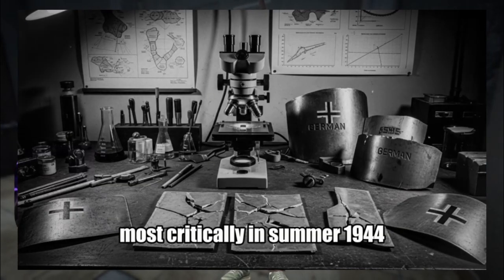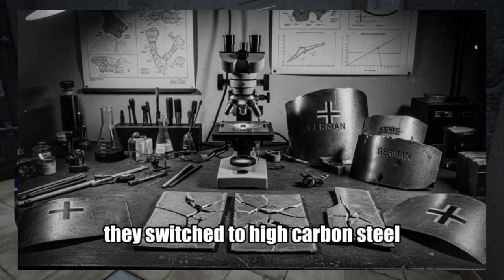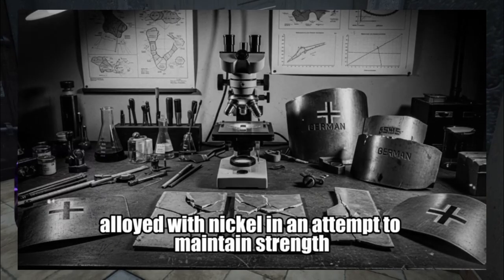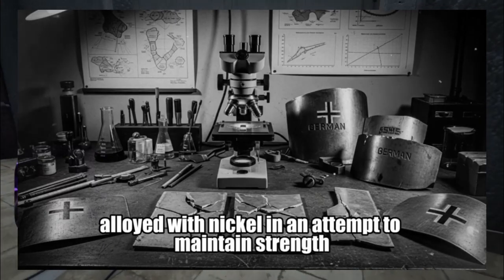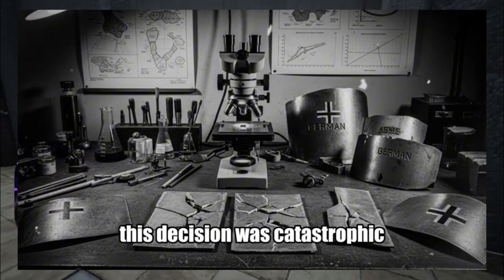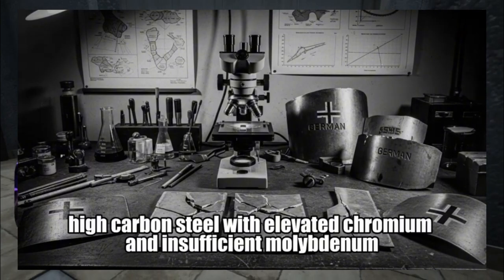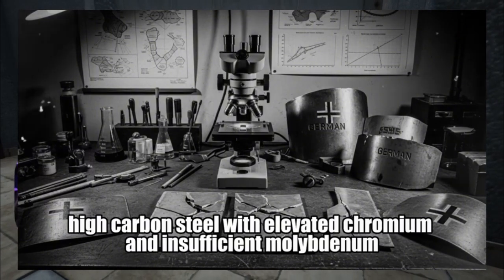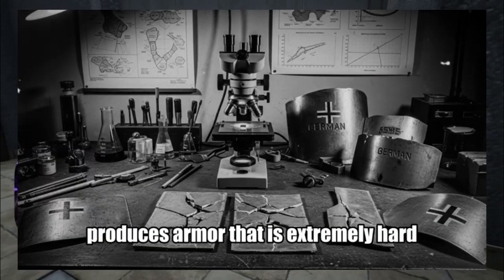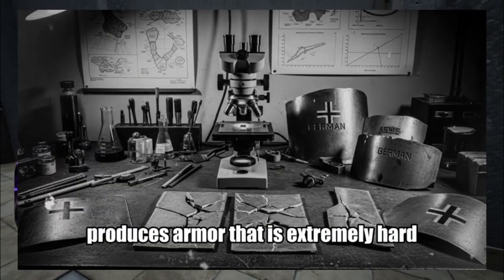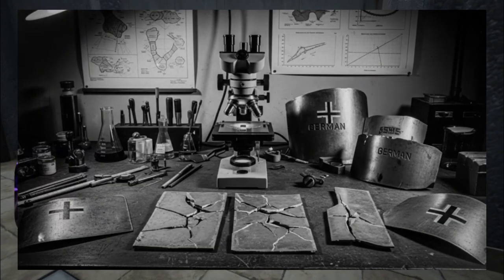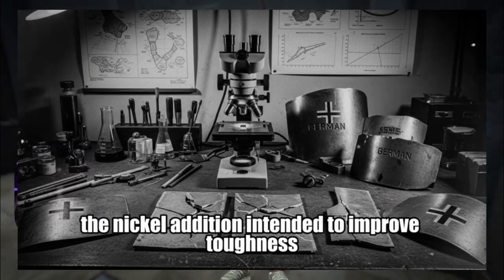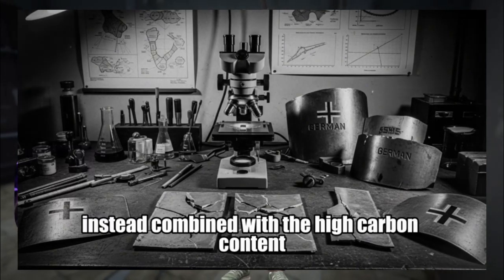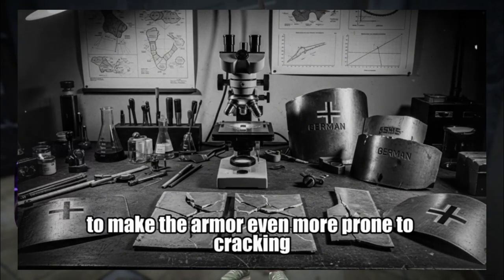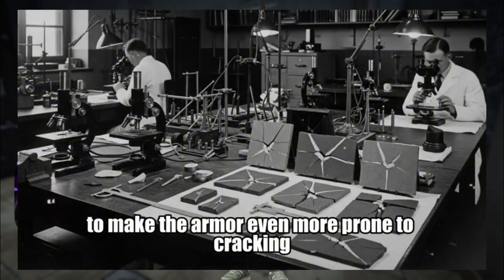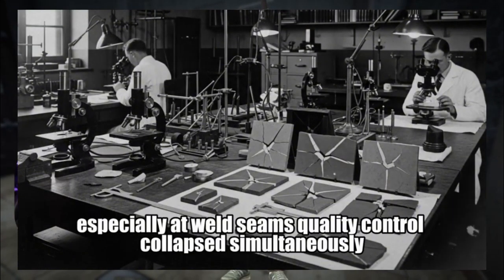Most critically, in summer 1944, they switched to high-carbon steel alloyed with nickel in an attempt to maintain strength. This decision was catastrophic. High-carbon steel with elevated chromium and insufficient molybdenum produces armor that is extremely hard but dangerously brittle. The nickel addition intended to improve toughness instead combined with the high carbon content to make the armor even more prone to cracking, especially at weld seams.